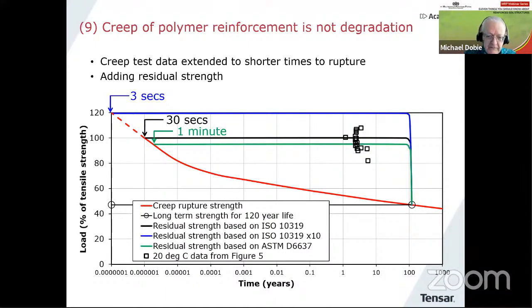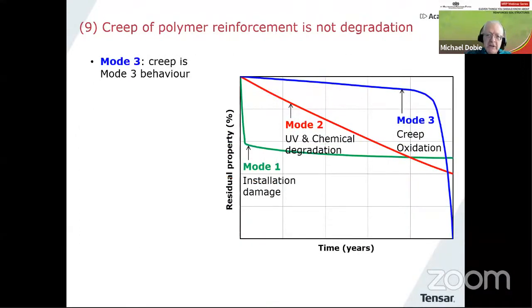If we followed the ASTM procedure, which is a slower test rate for tensile testing, it would be the green line. So one thing that's important to realize is that when you look at creep reduction factors, you need to be aware of the standard used to measure the tensile strength, because it can affect the creep reduction factor. Creep is absolute, but tensile strength depends on the procedure used to measure it. So just a little point to make from this.